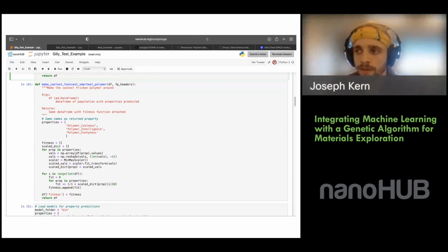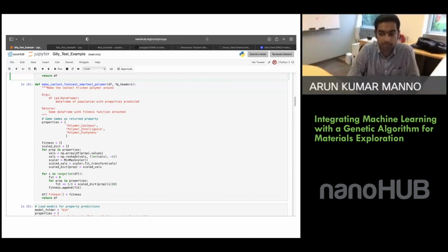For all of these, the biggest thing is that retrosynthesis algorithm. You make a bunch of these polymers, and a lot of them aren't synthesizable. Then you run them through some sort of retrosynthesis algorithm to predict which ones are most likely to be synthesizable. It might only be like 20 out of 10,000 polymers or something, just because of the nature of how these things work. Then you would send those to chemists who would try to synthesize them. So we're actively working on that right now, but we do have a general idea about which ones are more synthesizable than others.